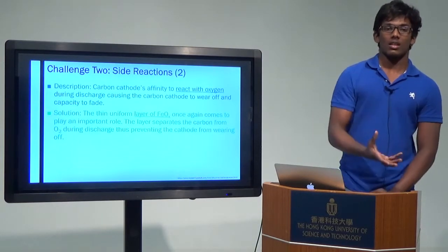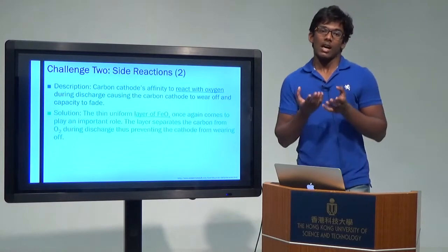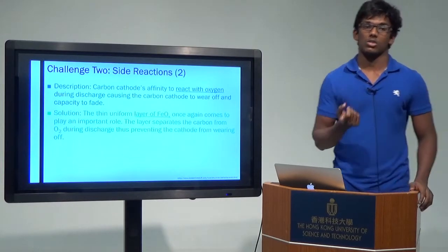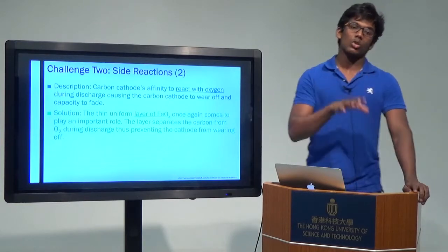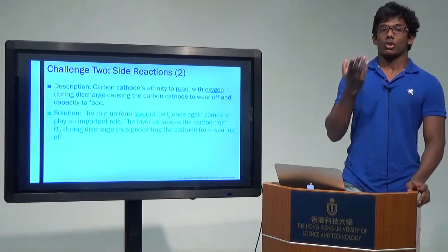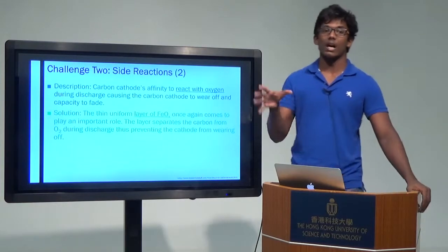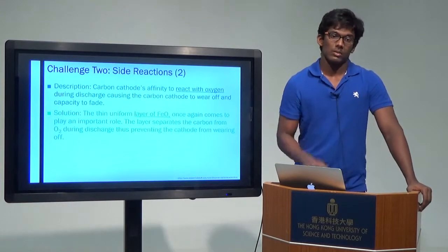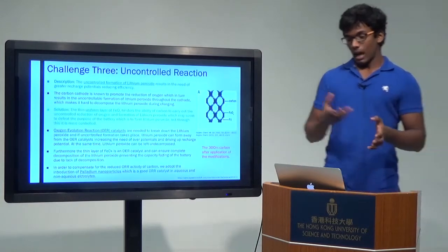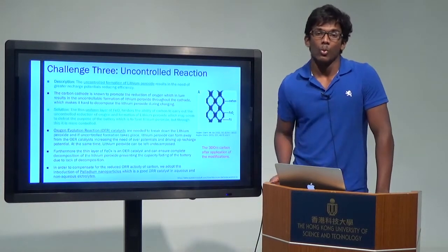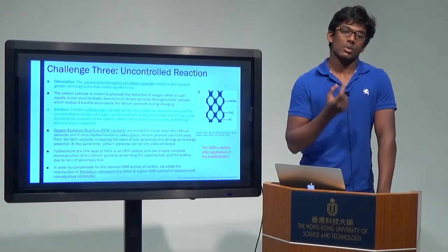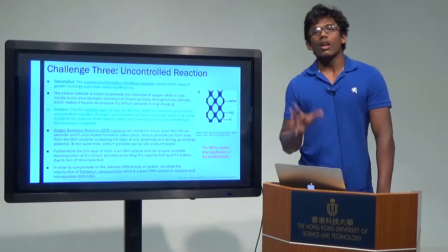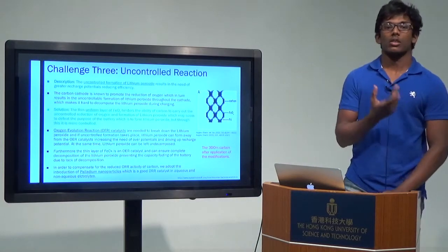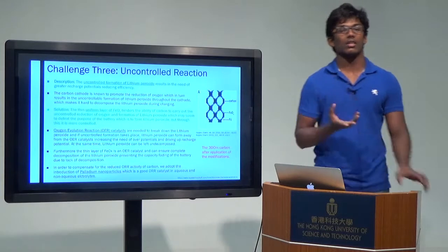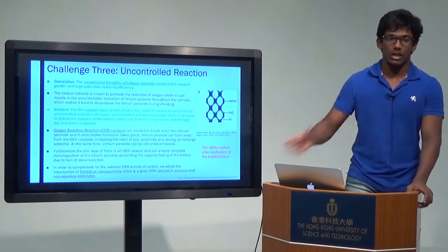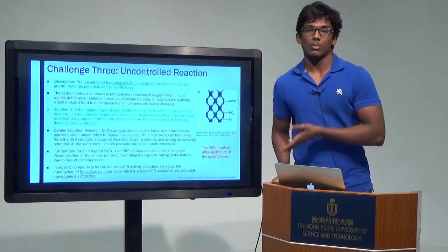Another problem with this lithium-air battery could be the carbon's affinity to react with oxygen during discharge, causing the cathode to wear off and capacity to fade. So for this, once again, the iron oxide protects the carbon surface from reacting with oxygen. Another problem would be the uncontrolled formation of lithium peroxide, which results in the need for greater recharge potential, reducing efficiency. As we all know, carbon is known to promote the reduction of oxygen, which in turn results in the uncontrollable formation of lithium peroxide throughout the cathode, which makes it hard to decompose lithium peroxide for us.